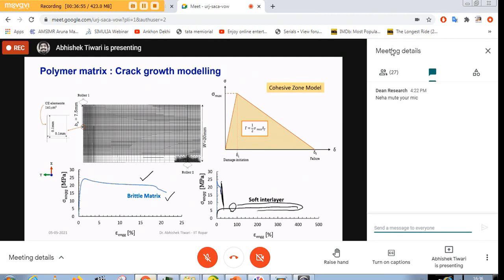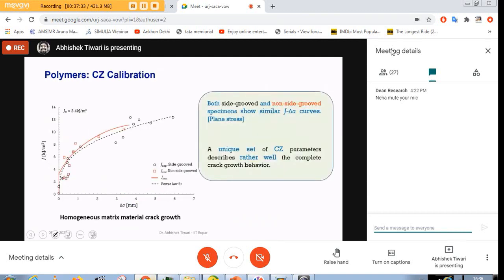We first model the homogeneous material using cohesive zone modeling. We chose this because it was very simple and it needs only two parameters for calibration, which are fracture energy and the cohesive stress. The cohesive stress we can guess from some value between the yield strength and the ultimate tensile strength, and the fracture energy we can guess from the initiation fracture toughness value. So we tested some homogeneous specimens, made the guess, calibrated the model and did the simulation to find out the J delta A behavior, and finite element analysis results using configurational forces were able to describe the behavior experimentally more or less closely.